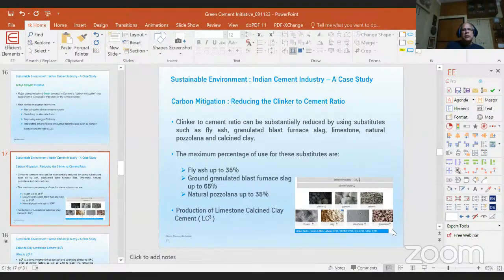Now, as far as carbon mitigation is concerned, the first point was reducing the clinker to cement ratio. As I mentioned, from a classical ordinary Portland cement, which has 95% clinker, you can go on adding cementitious material to ensure that the quality requirements, the setting time, the workability, the 28-day strength, the 7-day strength are still maintained. You have the adequate standards to produce this kind of cement. You can reduce the clinker. You can add fly ash, granulated blast furnace slag, limestone, natural pozzolana and calcined clay.